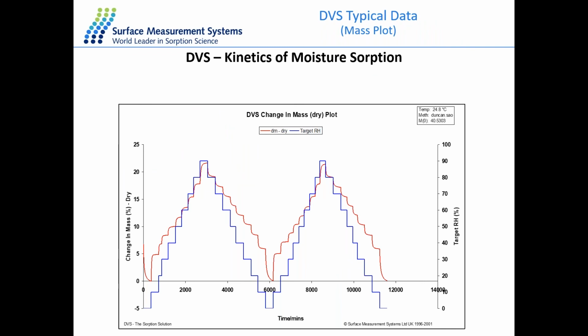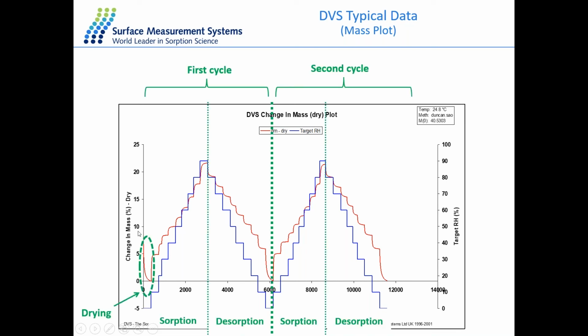So here I just want to show very typical data that you can get from the DVS instrument. The blue line here is for the target relative humidity that you increase from 0 to 90% RH with 10% intervals. And the red line is for change of mass for the sample. So at each stage, the sample is picking up the moisture, reaching equilibrium, and then it jumps to the next stage automatically. And the first stage here is just the flowing of the carrier gas for the drying of the material.